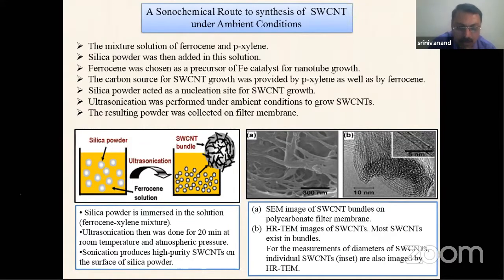Yesterday I had an opportunity to listen to the presentation given by Mr. Ram. I think he was talking about plasma, where he was telling the atmosphere plasma can also be made in the laboratory. In a similar fashion, we also did this experiment, and we synthesized the carbon nanotubes. All we need is a nucleating site, which is nothing but a silica powder, on which we were able to grow carbon nanotubes from ferrocene and paraxylene. Paraxylene and ferrocene are the carbon source, and your silica nanoparticle is the nucleating site. So we were able to get these carbon nanotubes.